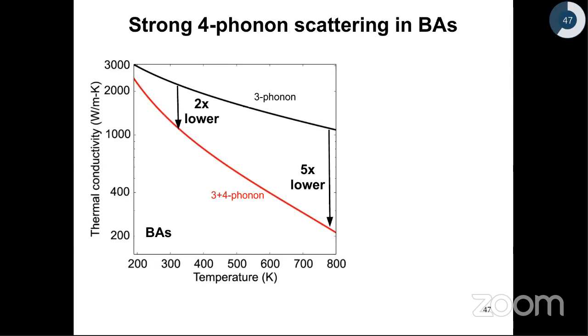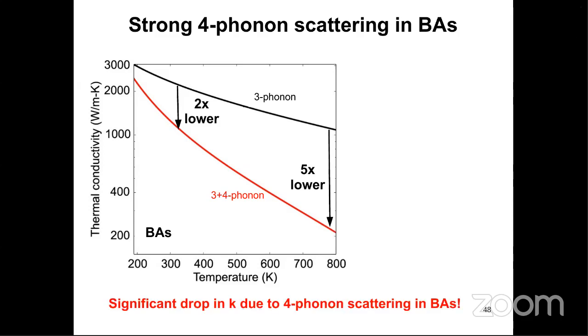If I include 4 phonon scattering, what happens is there's a dramatic decrease in the thermal conductivity from the 3 phonon value. In fact, at room temperature, you see that the thermal conductivity goes down by a factor of 2, and at higher temperature, it can go down by a factor of 5. So clearly, there is a significant drop and an effect of 4 phonon scattering on the thermal transport in boron arsenide.